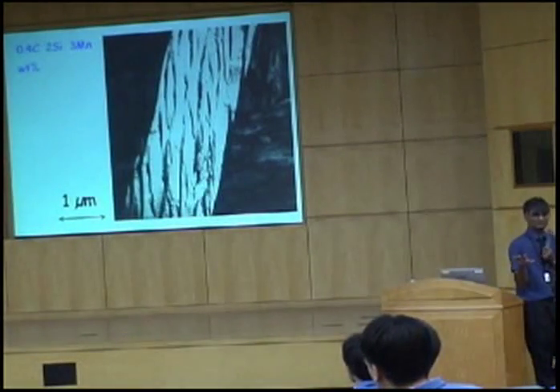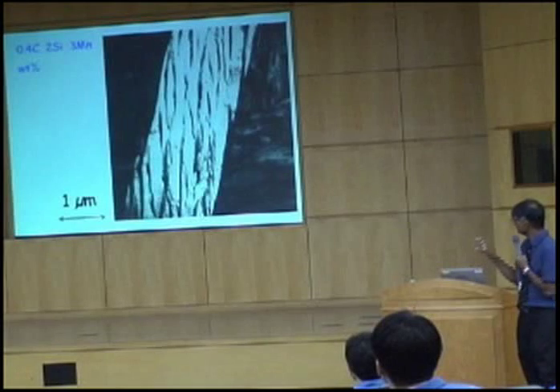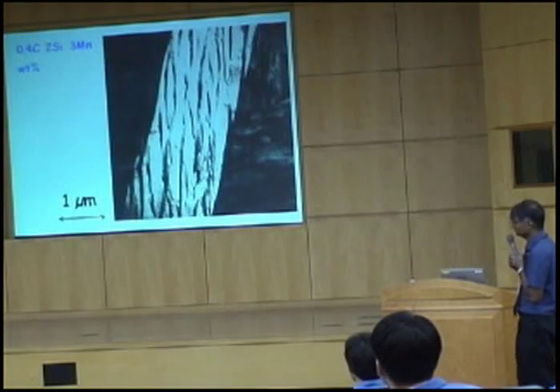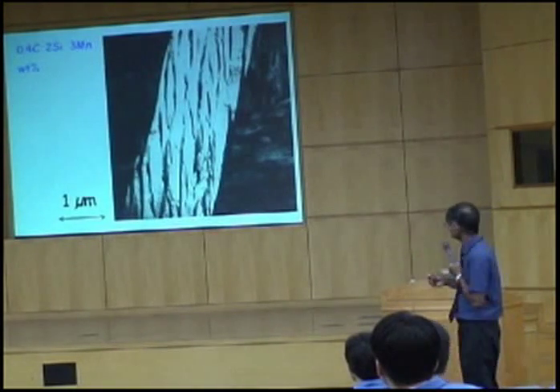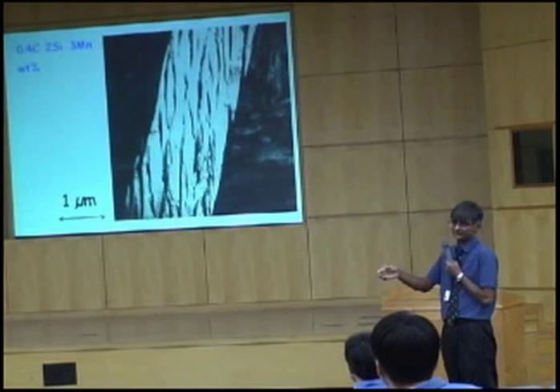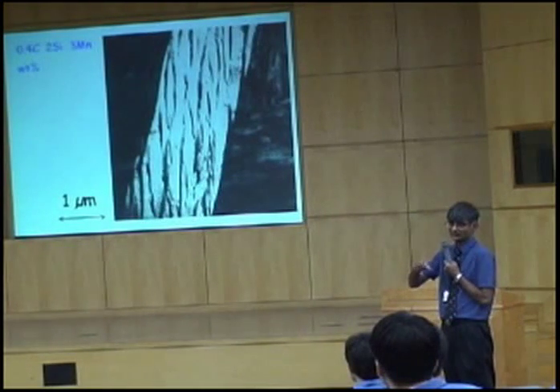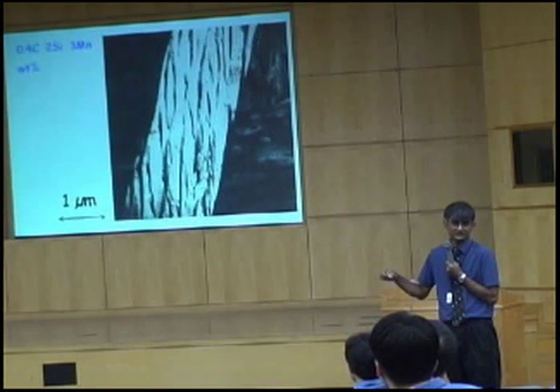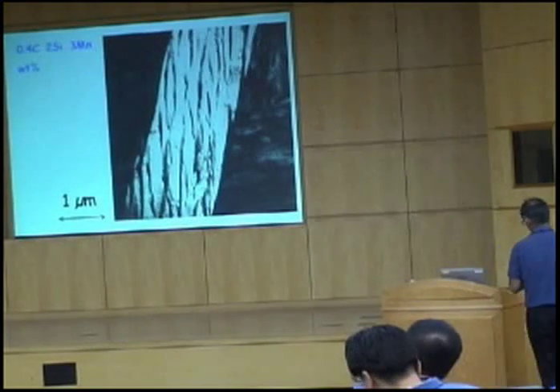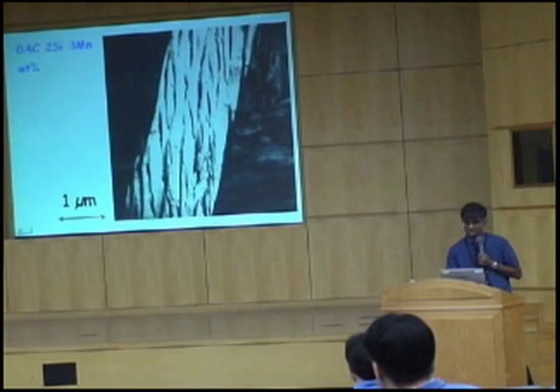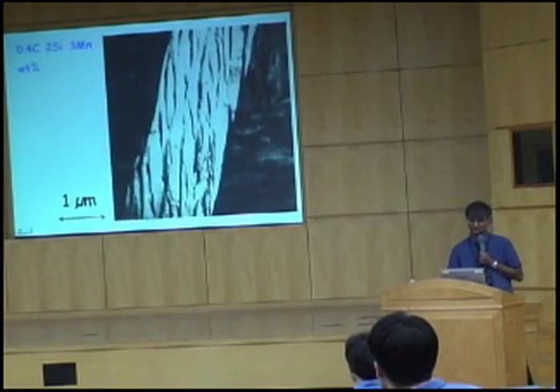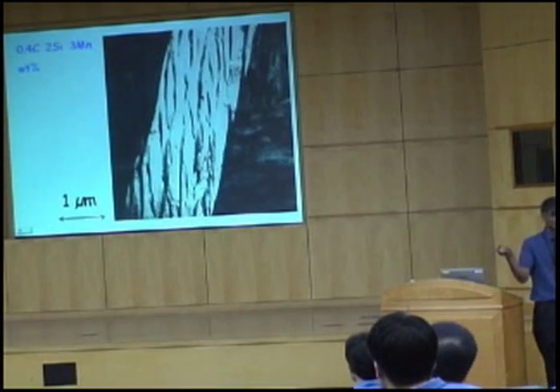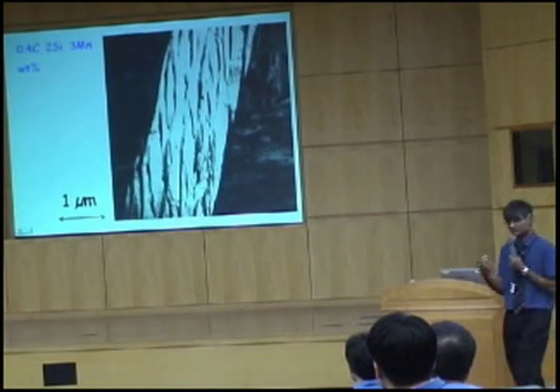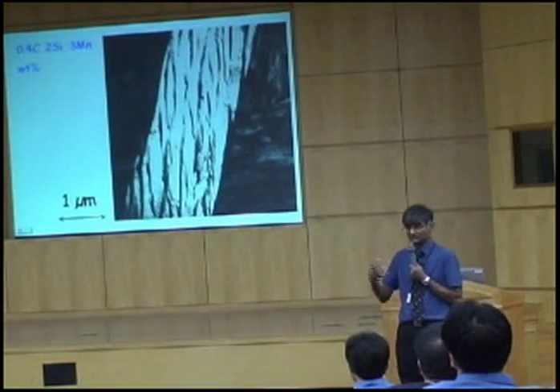So let's assume that we don't need to worry about silicon, and we produce this beautiful microstructure of bainite, where we have avoided cementite, and instead of cementite, we have carbon-enriched films of austenite. Okay, so these regions here are austenitic films, which are rich in carbon. We not only have this FCC phase between the plates of bainite, and remember I told you austenite does not have a ductile brittle transition, so this is good for toughness.